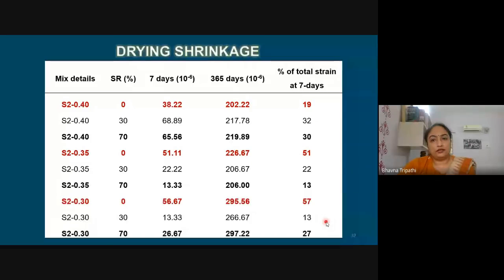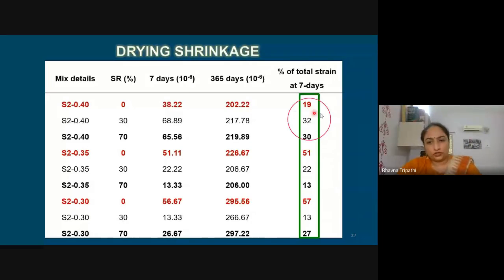Other mixes with a lower water cement ratio and a lower aggregate cement ratio also showed a similar trend, except for one mix, that is the 0.4 water cement ratio mix. Here the control specimen had developed less strain at 7 days in comparison to all other ISF slag mixes. However, all the other mixes of this series, which had a lower aggregate cement ratio, showed that the control mix has appreciably higher shrinkage strain at 7 days in comparison to all ISF slag concrete mixes.